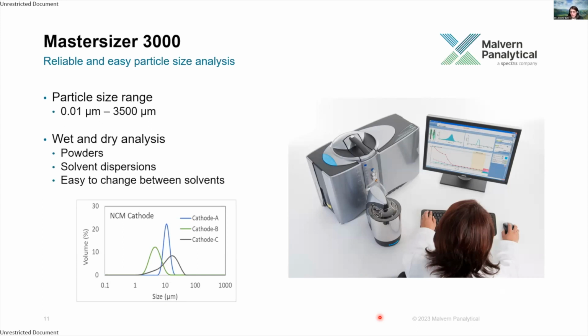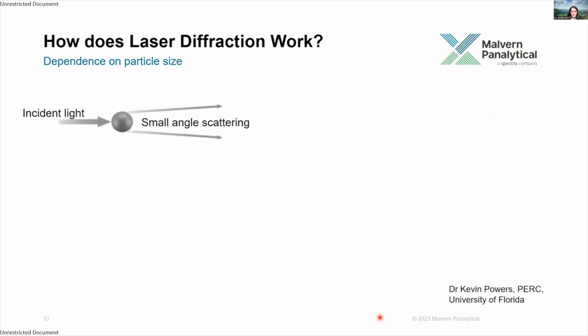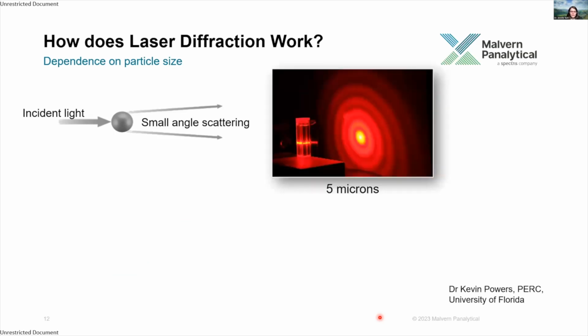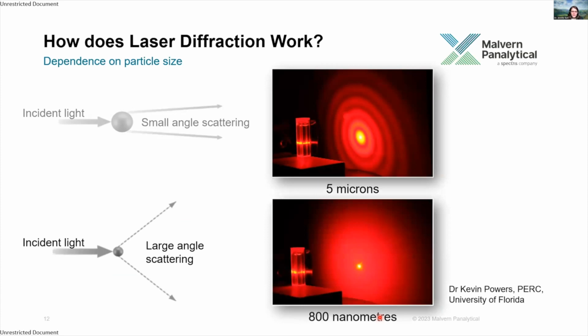So how does it work? In laser diffraction, we measure the light scattering pattern produced by particles illuminated in the laser beam. If we have large particles, we get mainly high intensity scattering over small angles. So this results in a ring pattern like the one shown here. And then as the particles get smaller, the angle of scattering gets wider and the intensity gets lower. And this then results in a much more diffuse scattering as shown here. So what we're doing with laser diffraction is we're measuring the intensity of scattered light as a function of angle.